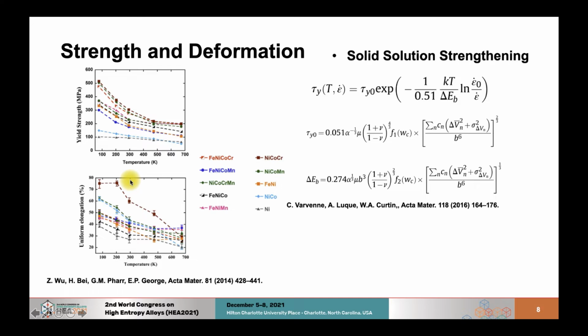And basically what Varvenne's model shows, that is probably the most widely used solid solution strengthening model for high entropy alloys, is that there are two things that really control the yield strength of these FCC materials: the shear modulus and the atomic size or the atomic volume mismatch. So the bigger these two terms, the higher the strength. And this term especially varies a lot from alloy to alloy.